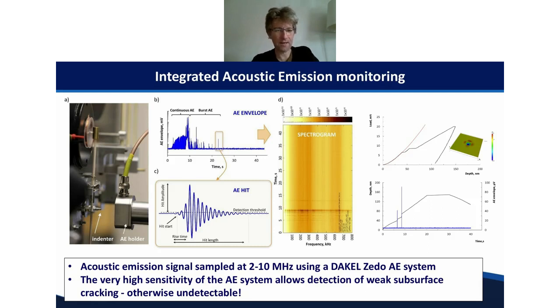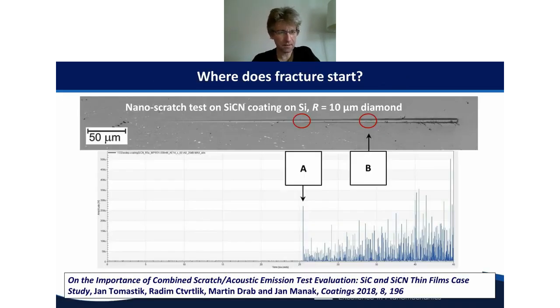But perhaps more interesting is it allows us to look at cracking events where we might otherwise not see any information. So this is an example of a very simple ramped load scratch test on a silicon carbonitride coating, a couple of microns thick, deposited on a silicon wafer, and this has been scratched with a 10 micron end radius diamond probe, and this is done by customers of ours at Palacky University in the Czech Republic. And what they found is the first visible sign of cracking on the surface is at point B, but we can quite clearly see in the acoustic emission spectrum that much earlier in that process some cracking has been detected by the acoustic emission sensor.